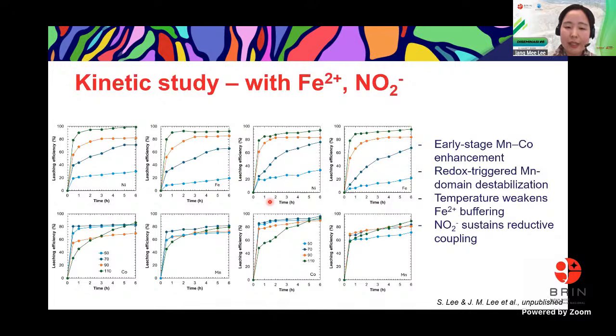When reductant is introduced, we had used 2 types of reductant, as I mentioned, ferrous iron and nitrite ion. And sorry, I didn't label the graph. So the left side is about the ferrous iron, and the right side is about the nitrite ion. So when reductant is introduced, the dissolution regime changes a lot as compared to the leaching test in the absence of the reductant. The manganese and cobalt extractions are strongly enhanced when we use the reductant, especially at the early stage. And this is consistent with the redox-triggered destabilization of manganese-rich domains.